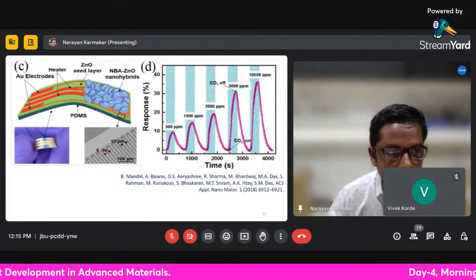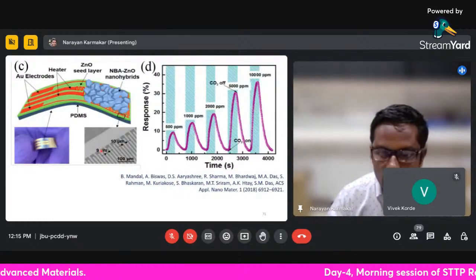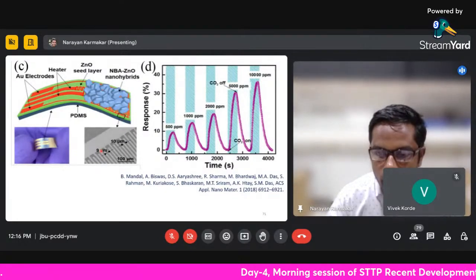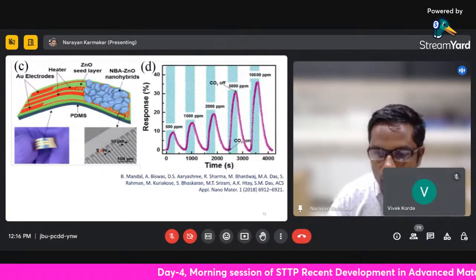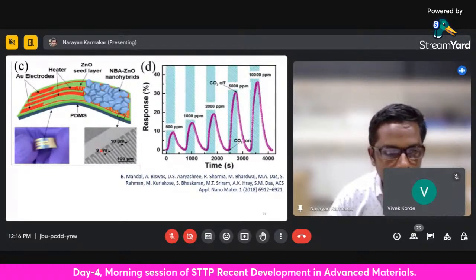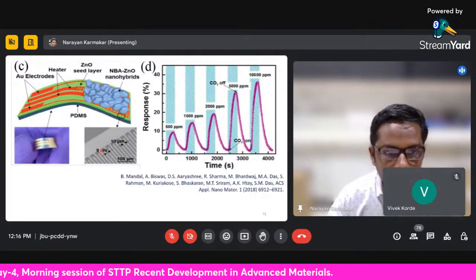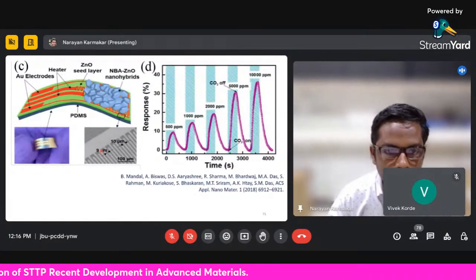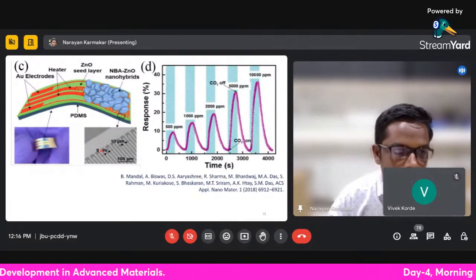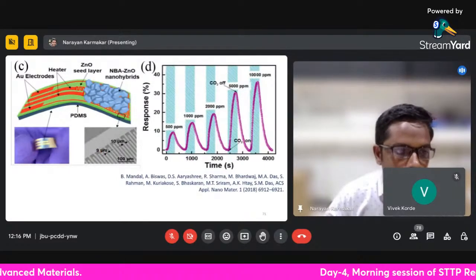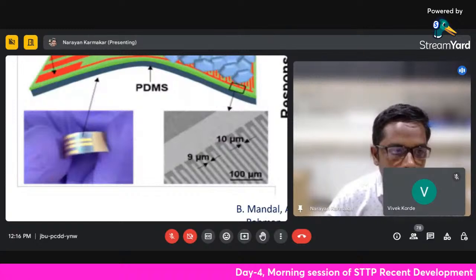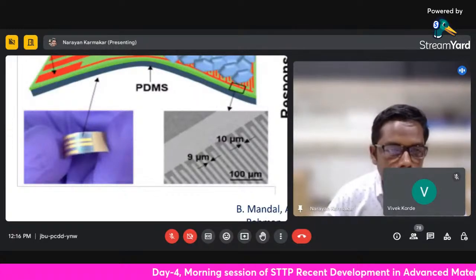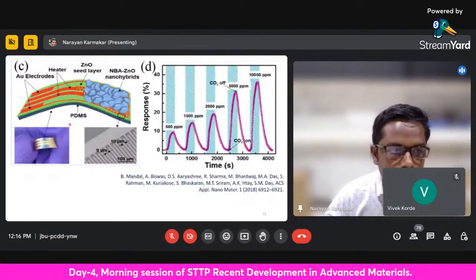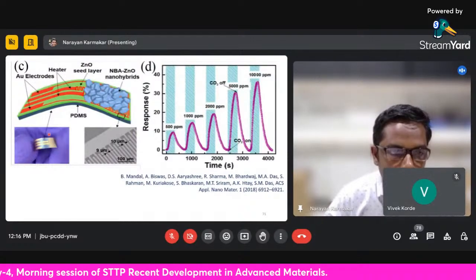again a flexible sensor where they have detected carbon dioxide, in which they were able to detect different gases for up to 500 ppm. This flexible sensor can be mounted on any device, and we can measure the response for different gases. This is only possible because of making use of this thin conducting polymer.